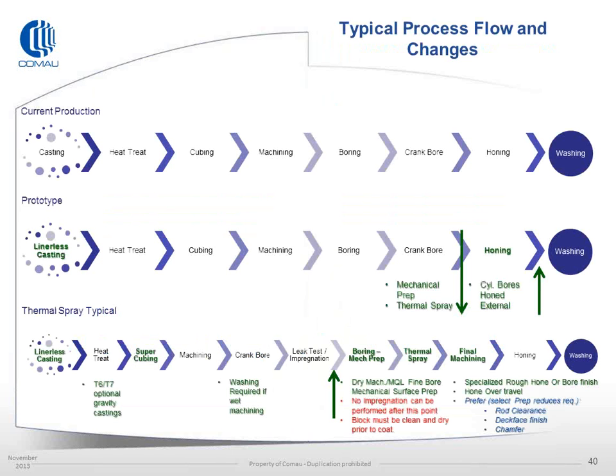In terms of manufacturing, a lot of questions are, well, can we not do that much sooner in the surface preparation in rough or even at a sub-supplier? Currently our recommendation is to focus in on the final machining, or if you have a very stable locating system, then you can do it much farther upstream. The main reason for this, and it has nothing to do with the PTWA in itself particularly, is when you're targeting a 100 micron surface, you have to take significant care on your locating features so that your true position for your bore centers, which is going to be set by the surface prep, is maintained throughout the process. So the sooner you cut that surface, the more care you have to take through the process in maintaining that position.